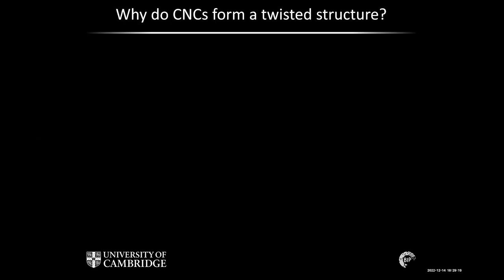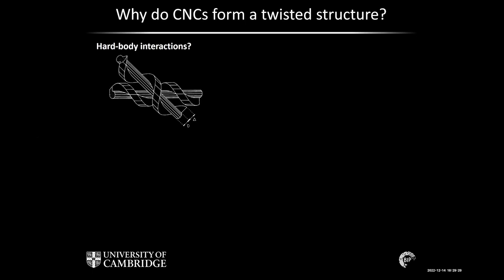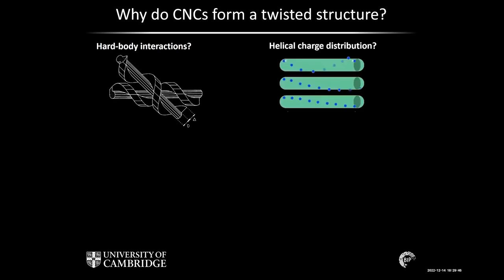Because there are a couple of theories which have been proposed over the decades to explain what might be happening here. So one idea is that the individual particles are somewhat twisted, or chiral, as we say, in shape, a bit like screws or fusilli pasta, and that essentially, due to hard body interactions, they prefer to pack together in a twisted fashion. Another idea is simply that the distribution of charges on each individual CNC is itself helical, and that this would lead to a twisted interaction.